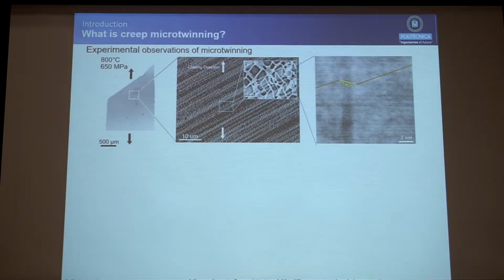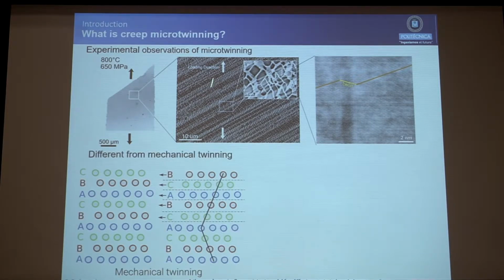So what is the difference between this microtwin mechanism that I'm going to explain and the mechanical twinning that everyone else is studying in other materials? So mechanical twinning is basically, this is kind of this microtwin mechanism that I'm studying. So they are really thin bands of a few atomic layers, and they're forming in parallel sets. And the difference with mechanical twinning is if you have here a mechanical twin, basically it is formed by continuous paths of partial dislocations that produce the same crystal structure, but just rotated, in FCC, for example, 60 degrees. But the lattice structure is again perfect.